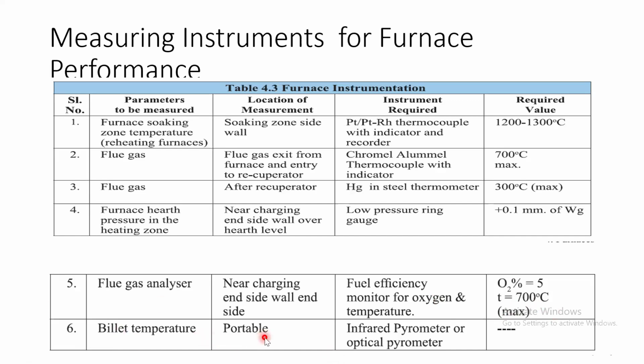Then billet temperature has to be measured at any portable location wherever the billet is in front of you, and you can directly use an infrared or laser pyrometer or optical pyrometer. The required value of the billet temperature is dependent on the location where you measure it. If you measure it at the entry before heating, the billet temperature will be atmospheric. But if you measure the temperature after it gets red hot, the billet temperature will be around 500 degrees centigrade or so. So this is the overall judgment, and these are the measuring instruments used for measuring the furnace performance.